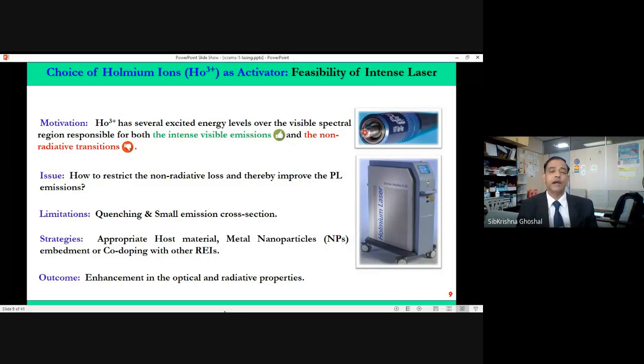So when we put this kind of nanoparticle inside the glass ceramic and then bring the rare earth in front of them, an interesting thing happens. A plasmon-mediated effect happens. This plasmon-mediated effect can push the absorption and emission cross-section of the rare earth very high. So then we are going to see some enhancement or increase in the optical radiative properties. That means the stimulated emission cross-section would be getting enhanced. That means we'll get very high or intense photon emission from the material.